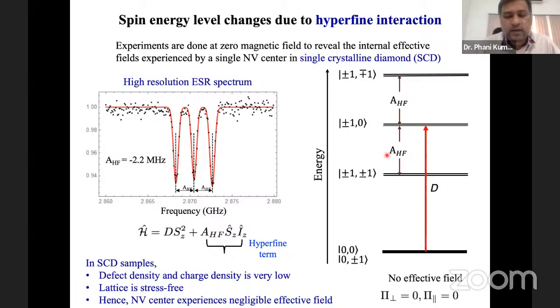So first of all, we turned to the single crystal diamond samples, which we know are ultra pure. There are hardly any charges. They are very stress free. And then we performed the high resolution spectrum, and we see these three nice resonances which are equally spaced, and this is perfectly understood by the community. And this is because there is no effective field and so on.